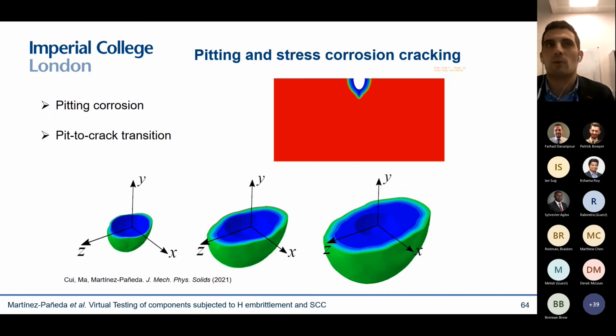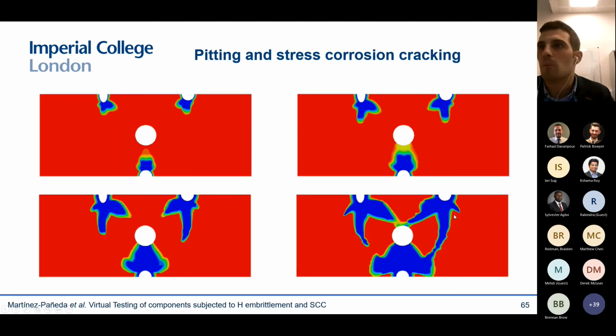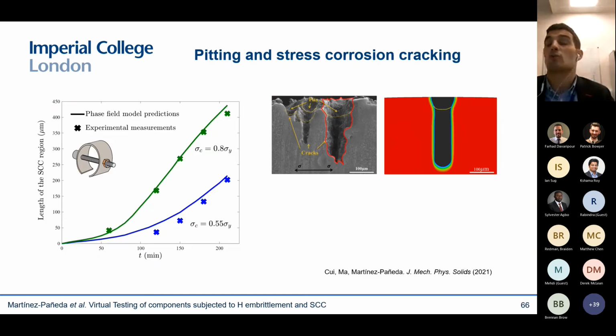And I just want to say that we can capture pitting corrosion and pit to crack transition. You can see here the pit to crack transition, which is something that, in the corrosion community, we have been trying to model using finite elements for a long time. And we can do this in problems of arbitrary complexity. You can see a pit here growing in 3 dimensions. You can see here multiple pits interacting with each other. And you can, of course, also see here a quantitative comparison with experiments.